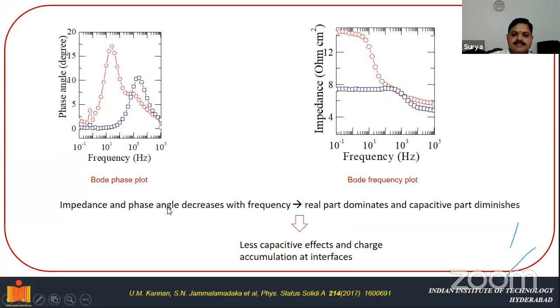In the Bode frequency plot, the impedance and the phase angle decrease with frequency. From these two graphs, we can say the impedance decreases. This red colored graph is for titanium dioxide. The blue colored graph is for the Ho2O3 device, holmium added titanium dioxide. The impedance decreases as soon as we added holmium to the device, and the phase angle also decreases. The real part dominates and the capacitive part diminishes. The real part is huge, and the capacitive part diminishes.